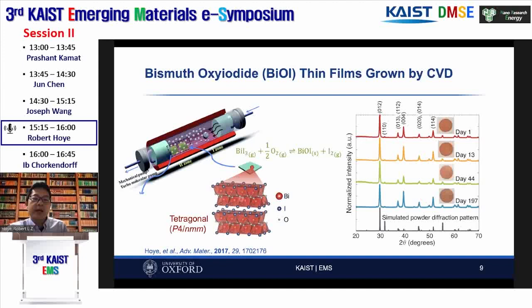So it's electronically analogous. We made this material using chemical vapor deposition, which is a technique that would be used commercially. And we grew these materials by evaporating bismuth iodide and reacting with oxygen gas to form bismuth oxyiodide thin films. Here you can see photographs of these films, and we kept these in ambient air for almost 200 days. And you can see that the phase remained exactly the same over this period of time. There's very little change in the visual appearance. This material is a lot more stable than methylammonium lead iodide perovskites in ambient air.